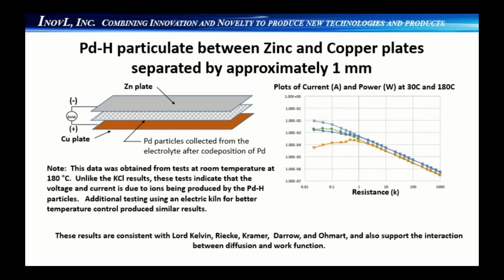While waiting for the thorium dioxide to arrive, we decided to conduct another test using the same cell configuration as we had used on the potassium chloride test. For this test, we used palladium hydrogen particles produced during co-deposition that either didn't attach or were ejected from the electrode and settled to the bottom of the electrolyte. The particles were collected and placed on a flat copper sheet and allowed to dry, aided by a heat gun to make sure they were dry.